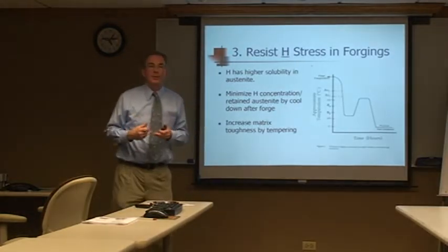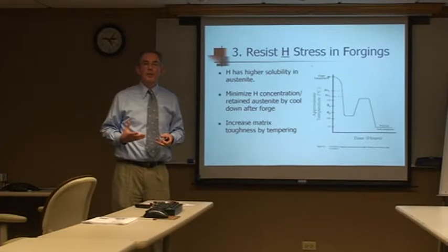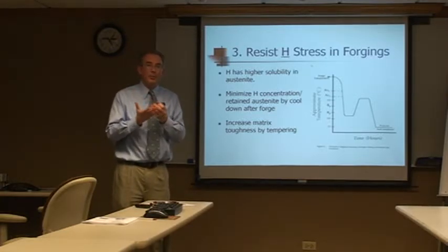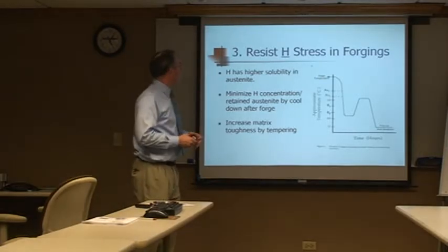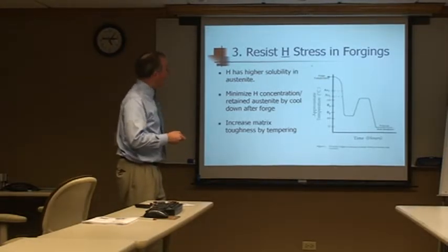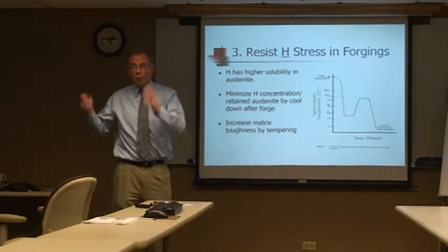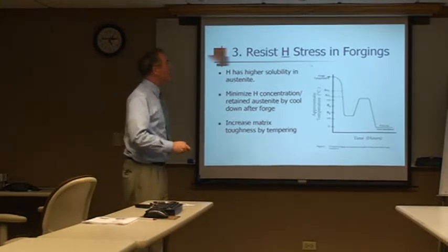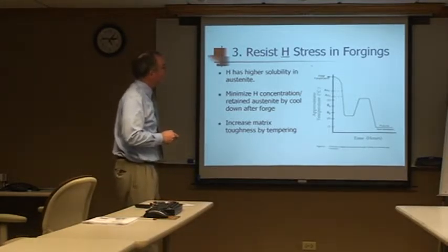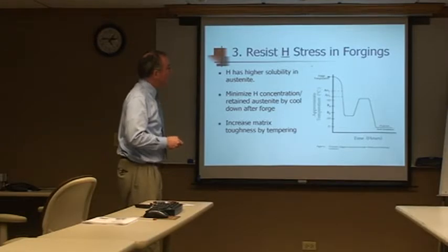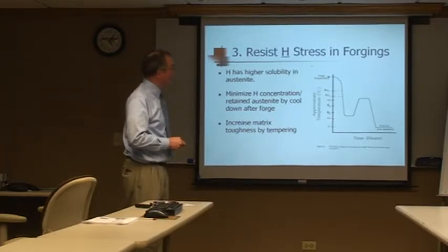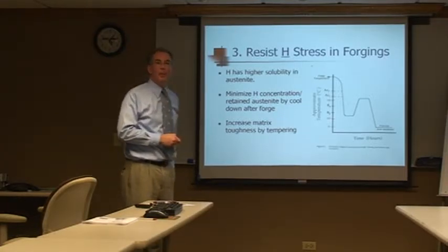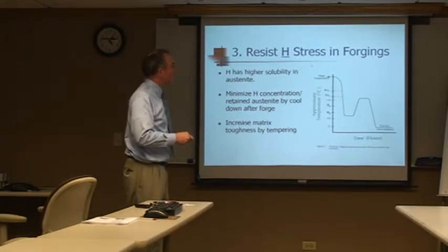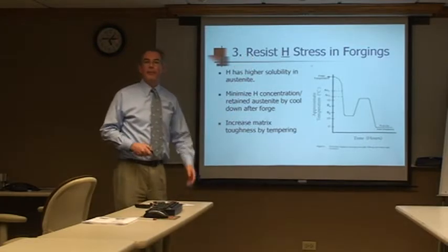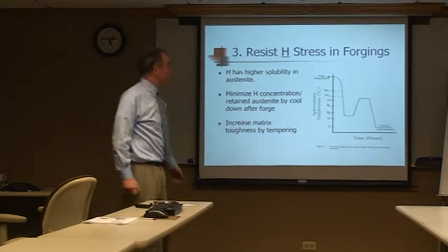If you have a brittle matrix because of the microstructure, it's going to be less resilient to the stress that's created. So what we can do, once forging on flake-sensitive grades and section sizes that are deemed to be of concern, is cool as fast as we can, air cool, and fully transform the steel to usually about 500 degrees Fahrenheit. Then we come back and give it a 1200 degree temper, basically tempering the matrix to make it more resilient, and then air cool, and send it on for either further heat treatment or further machining, whatever may be happening next.